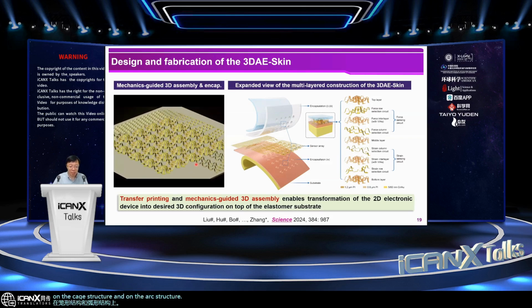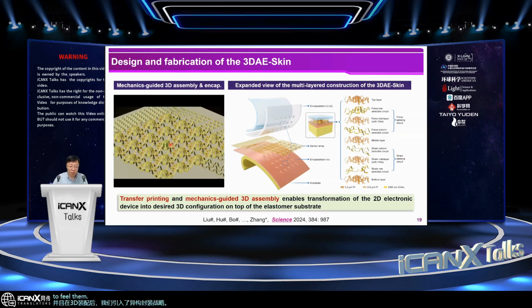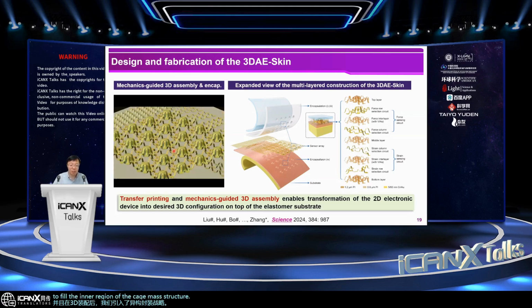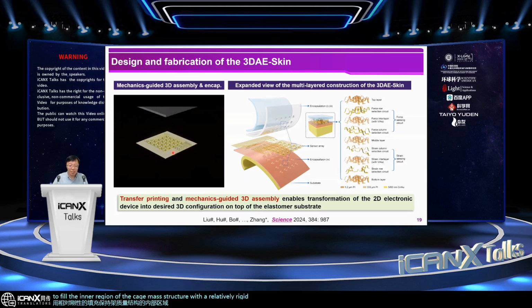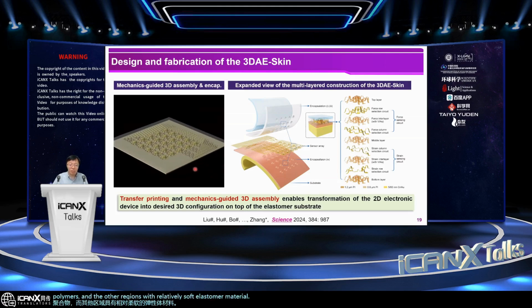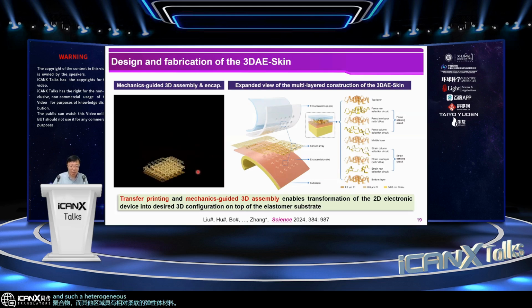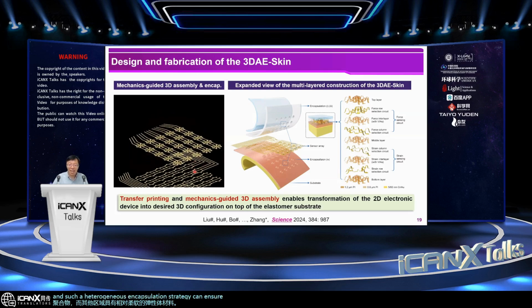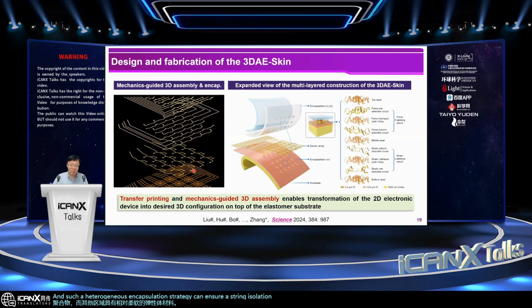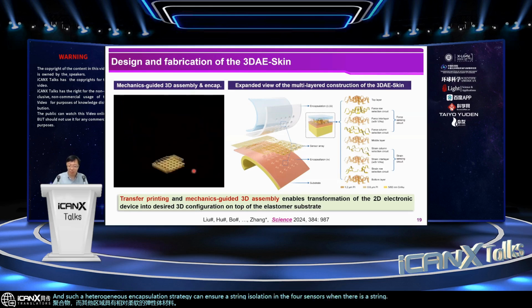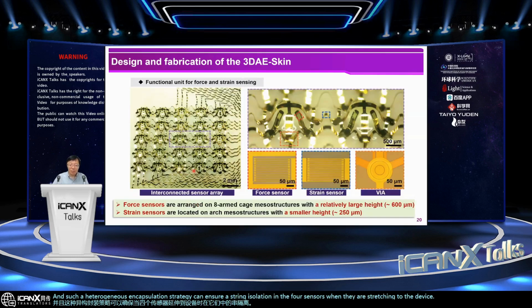And after the 3D assembly, we introduce a heterogeneous encapsulation strategy to fill the inner region of the cage mesostructure with a relatively rigid polymer and the other regions with relatively soft elastomer materials. And such a heterogeneous encapsulation strategy can ensure a strain isolation in the force sensors when there is stretching to the device.